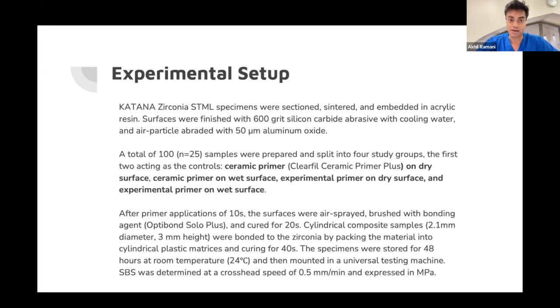So the experimental setup: we had zirconia that was section sintered and embedded in acrylic resin, and then this was polished with carbide abrasive and then sandblasted. A total of 100 samples were prepared and then split into 4 groups. We had the ceramic primer on dry surface, ceramic primer on the wet surface, using the Clearfil Ceramic Primer Plus, which is relatively the industry standard these days, at least in the clinic here at Penn. And then the experimental primer on the dry surface and on the wet surface.